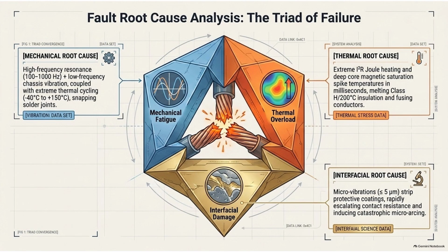The pressure builds, and as the microscopic vibration continues, there will be a fraction of a millisecond where those two oxidized contacts momentarily separate. Just a microscopic gap. The gap might only be a few micrometers wide, but because the electrical pressure, the voltage, is so high, and the current has nowhere else to go, it breaks through the air gap. It ionizes the air and creates a microarc. Like a miniature lightning strike inside the connector. Precisely. A highly localized plasma channel.